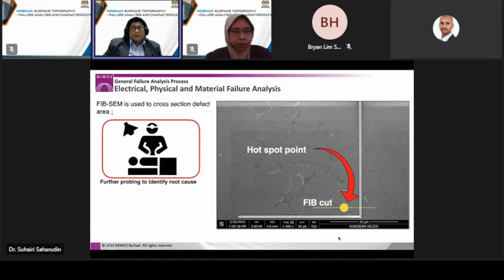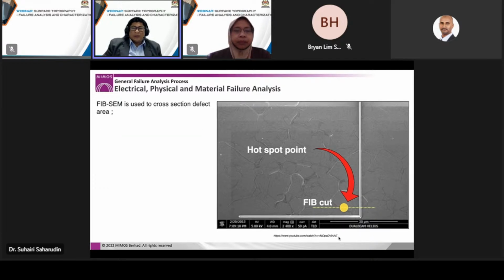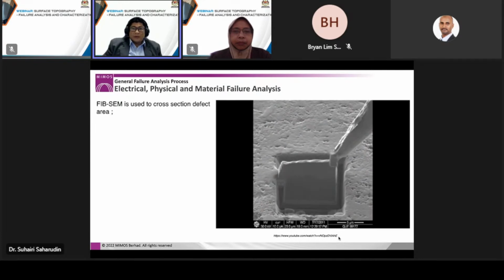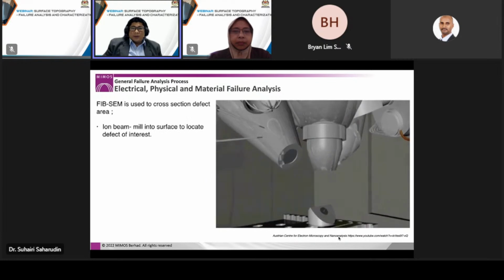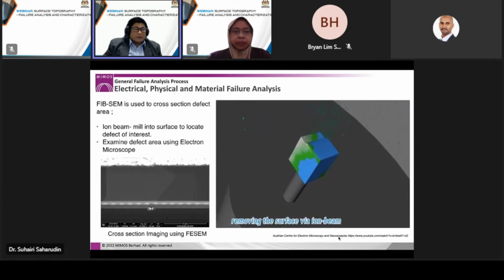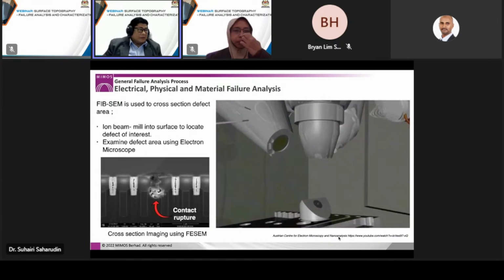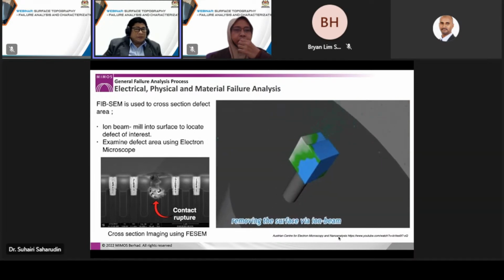Of course, a fault isolation result will be just an image without much information in it if no action is taken upon it. So the decision of whether you have to go to the operation theater very much depends on the nature of the investigation. In this case, once we get permission from our customer, we will perform the next level of diagnostic. For example, we can perform a FIB cut to create a shape known as a lamella, using a focused ion beam to etch or mill a specific area in the specimen. The prepared lamella can then be analyzed further by electron microscope, in this case to reveal contact rupture at the localized area, which indicates a possible cause of a short circuit.